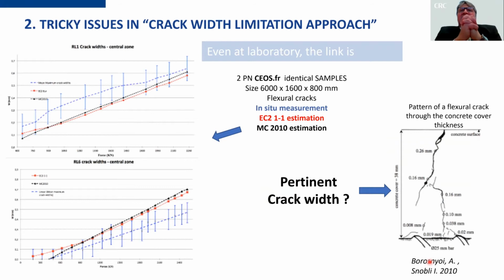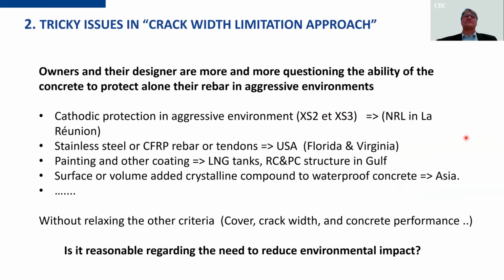Even in laboratories, the link is tenuous. These are some results of the last national project called CEOS.fr with large samples, 800 millimeter deep, 1.6 meter wide, in flexural crack. And on two identical samples, on one, all the cracks were above the calculation, and on the other one, all the cracks were below. And also, we can ask, with this kind of crack pattern, if the surface crack is really pertinent.